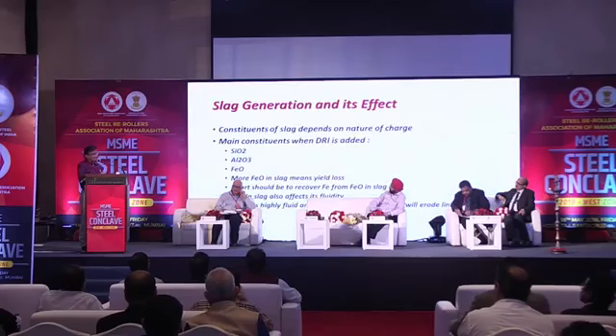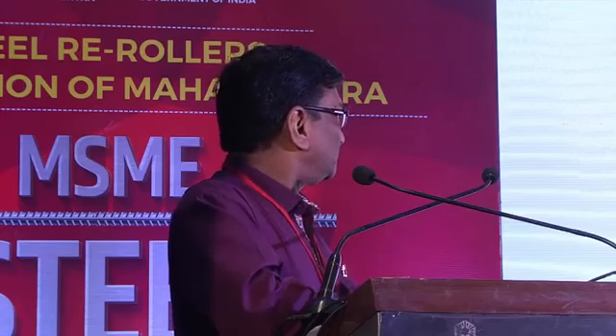analyze. And then, see, for Raipur sector, maybe 80% sponge iron use is very normal. But in Gujarat sector, 80% sponge iron may be a very bad choice. Slag generation and its effect. Here, one point which will come into further discussions also. Because this slag contains more and more of FeO content. So how to utilize that? FeO means almost 80% iron. So why not, either in situ within the process or outside the process, how we can utilize it?